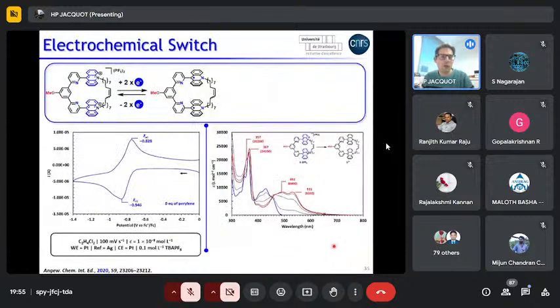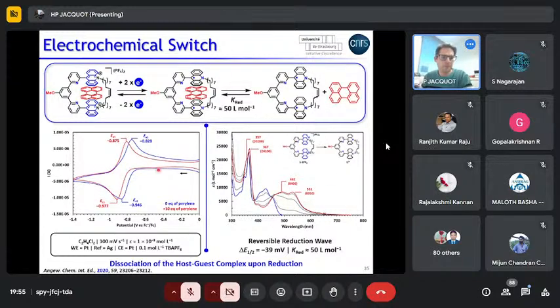We also looked at the electrochemistry of the macrocycle. It has a first reversible reduction wave, which corresponds to the injection of 2 electrons, 1 per acridinium, as supported by spectroelectrochemical data. And then when you add perylene to the solution, what you see is that you have a shift of the reduction potential towards more negative values. And this makes sense because perylene gives some of its electronic density to the acridinium cores. So basically, they are less prone to accept electrons from the electrode. And that's why you shift the potential towards more negative values.